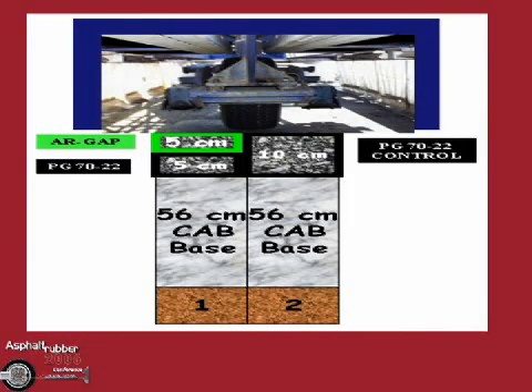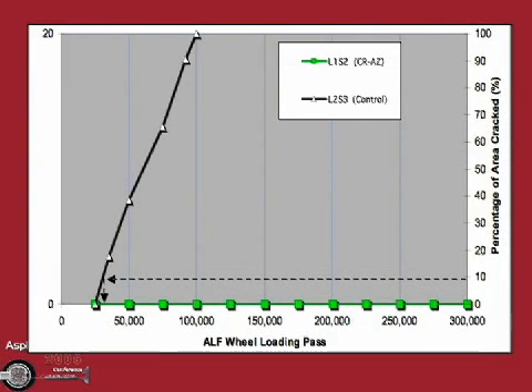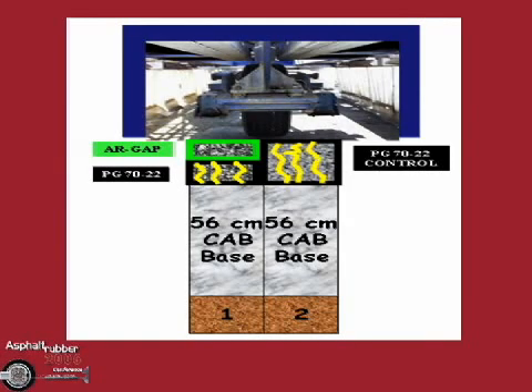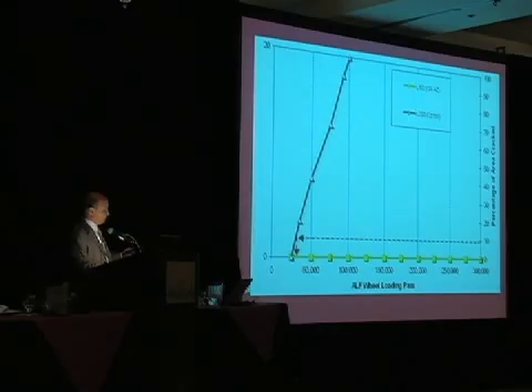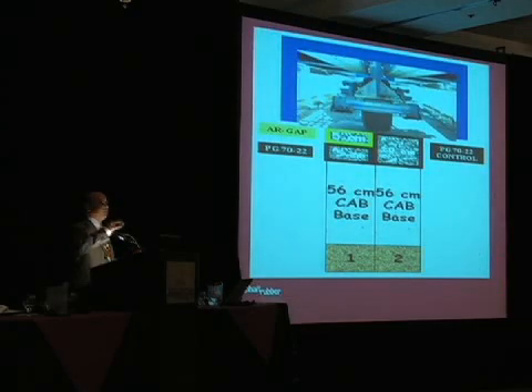We know, it is reported, that we had at least these two materials, conventional and asphalt rubber, and it was reported that one did not crack and the other cracked. Now, first, I want you to think that the difference in price in these two materials is not tremendous. I made an analysis for China, and if you design a pavement with this traffic, it costs maybe 20 RMB. RMB is the unit, forget it, say $20, for 1,000 trucks. If you use this structure based on this graph, you basically take the same amount of traffic with $2. It's a 10-to-1 difference.